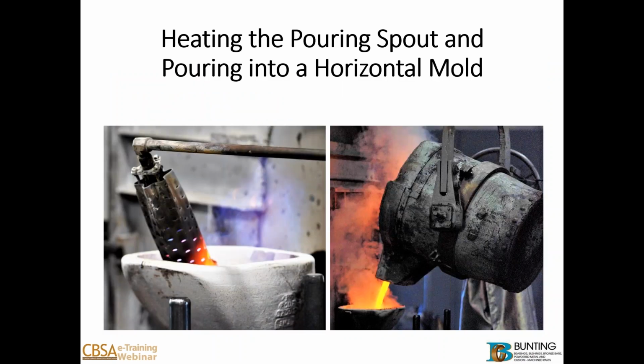To give a little more information, or at least a more visual on what's happening, if you'll notice on the left picture there, it's what we call heating the pouring spout. That's essentially, as you can tell by the right picture, where we pour from the ladle into the spout. The spout's basically a holding area for metal as it flows through the spout and into the mold. And in this case, this is a horizontal die. If it were a vertical die, it would come straight through the top. But in this case, it's basically a reservoir that allows the material to flow uniformly into the mold itself. But again, it really comes down to having all the right temperatures and the right chemistries. And the person pouring metal really worked hard to make sure he's pouring in a very specific way, keeping it uniform and consistent.